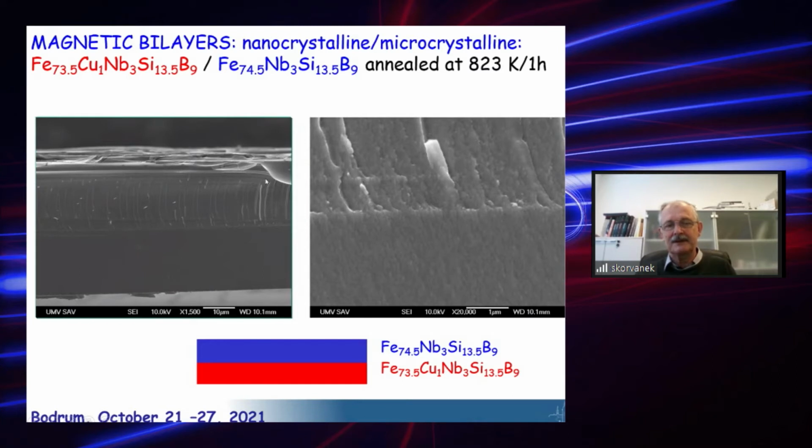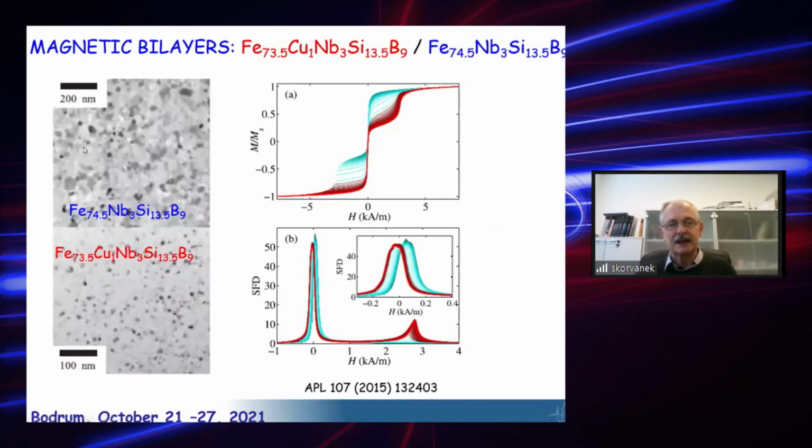It means we have bigger grains. Here we have, in higher magnification, the interface between these layers is very sharp. We can see it, and here we see how it is. Here this fine met layer exhibits very fine grains, around 10 nanometers, and this layer exhibits bigger grains. So here we see that bigger grains in such a case means that the structure is not efficient enough